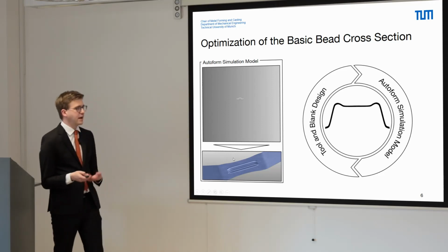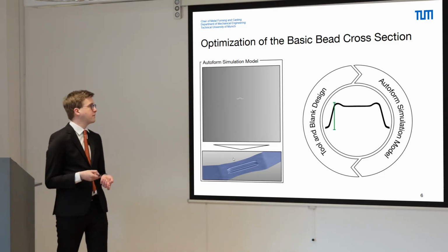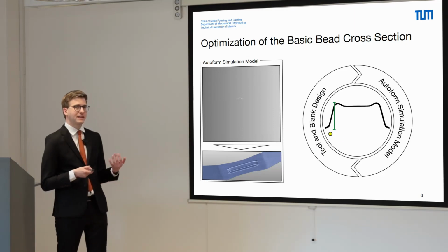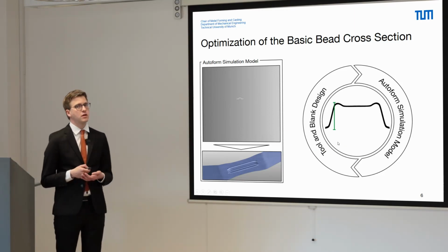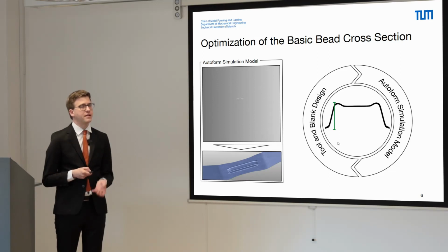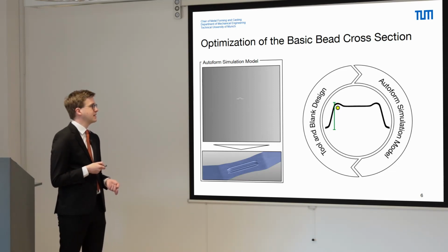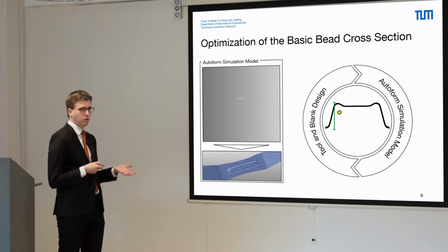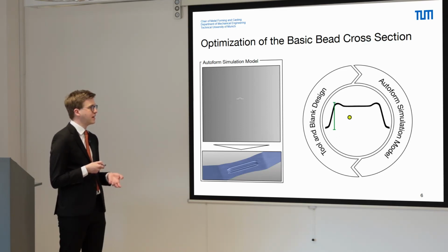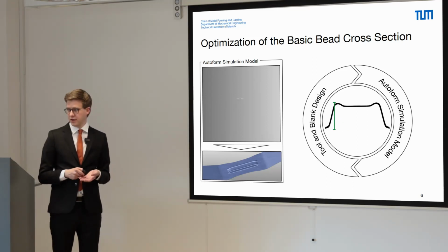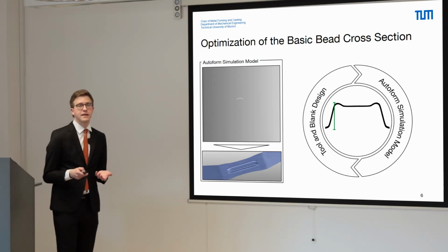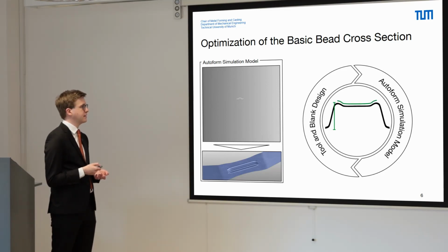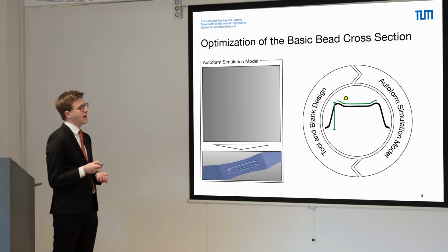picture below. Actually, the design of the bead cross-section is more of an iterative process, since several optimization goals have to be met. First, it's an increase in the manufacturable bead height without the occurrence of tearing, since a larger bead height is associated with a larger stiffening effect of the bead. The second optimization goal was to increase the upper surface area of the hybrid bead, since this is the area where the